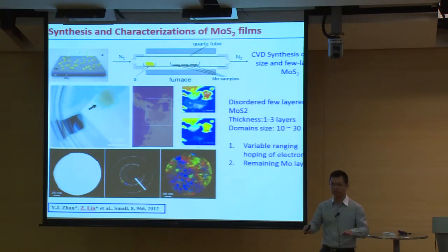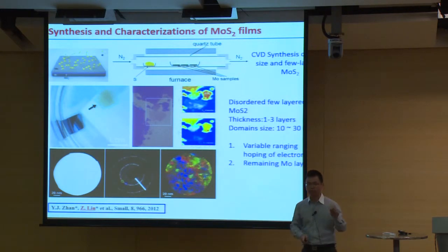to make monolayer molybdenum sulfide few layers. It's really time consuming, and probably you can get only a few devices in 1 week. So we are thinking, can we use a CVD method to make larger areas and reasonable quality samples? So at the very beginning, we deposit a very thin layer of moly on the silicon oxide, and then we introduce the sulfur to start reacting these materials at 800 degrees. And what we can get is 1 centimeter square molybdenum sulfide.